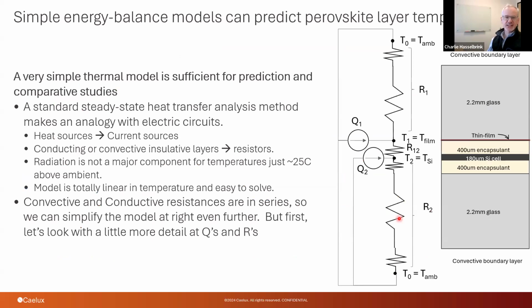So if you look at one of these systems, what's interesting is that we're working in the space of perovskite tandems over silicon. With the perovskite tandem over silicon, we have two absorbers, and of course they absorb at different wavelength ranges. So a portion of the spectrum is absorbed by this thin film. There's a 400 micron nominal encapsulant between that and a silicon cell, and you have some more encapsulant and glass.